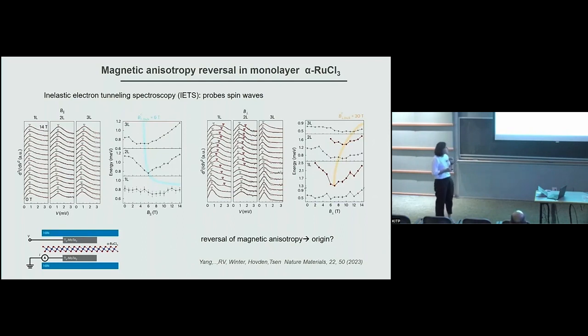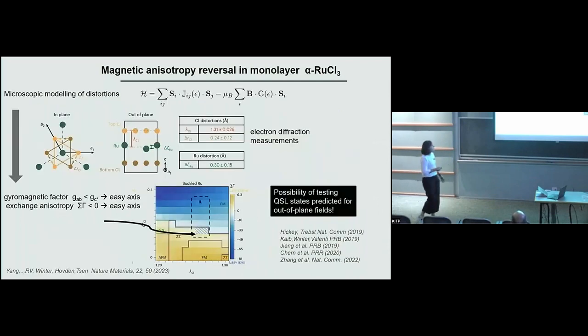So if there is a reversal, where does it come from? What we did, in fact, is that there are electron diffraction measurements that find there are some distortions in the monolayer, like small ruthenium buckling, as well as the chlorine in the planes coming nearby. And if you do the calculation with these distortions, indeed what you find is that the system shows a gyromagnetic factor along the z-axis, and the exchange anisotropy also changes sign. So this would be a very interesting platform.